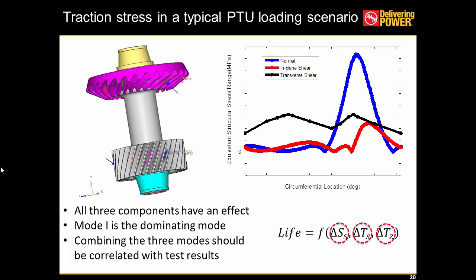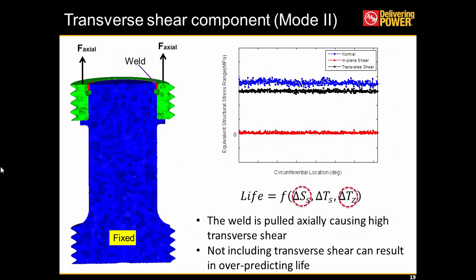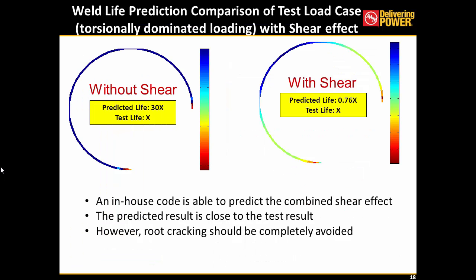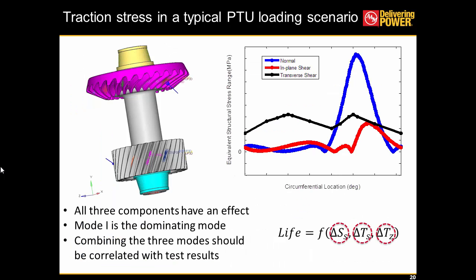My final slide discusses the combination of all this, which is a very common scenario in our PTU. As you can see from the slide, in this case the normal mode is the most dominant mode, but the shear terms are also contributing to the life. If we don't account for the shear components, then our prediction will be away from the variation band.